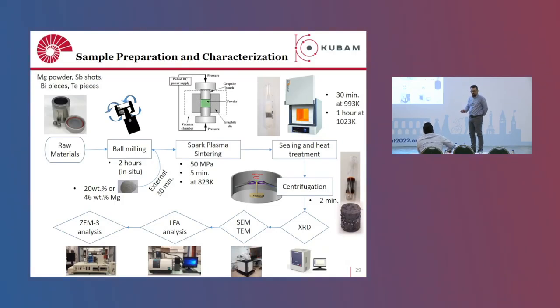Okay, so you can tune the properties by adding sodium or other elements, because magnesium is 2 plus here in magnesium 3 antimony 2. If you add sodium, you are replacing 2 plus with 1 plus, so you are pushing it towards a p-type material. Our motivation here is not to touch p-type, because we know that p-type ZT is much lower than n-type ZT. That's why we were focusing on magnesium, not adding any alkali metals. But you are right, instead of magnesium, you can dope with calcium, 2 plus. Maybe you can lower the thermal conductivity even further. We didn't do it, but this is doable. It's a meaningful strategy. The only thing is that maybe you will end up with calcium antimonide as opposed to magnesium calcium antimonide, because magnesium antimonide and calcium antimonide, separately, are very stable phases.